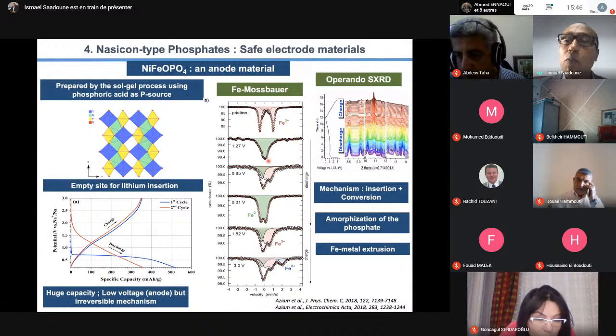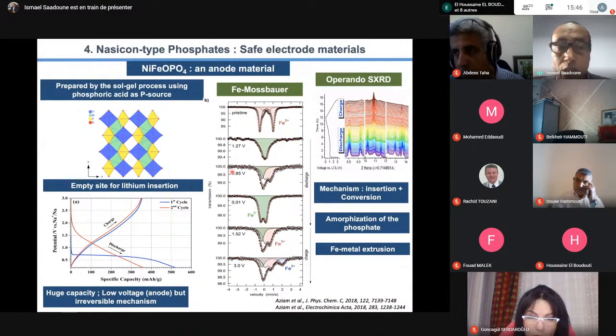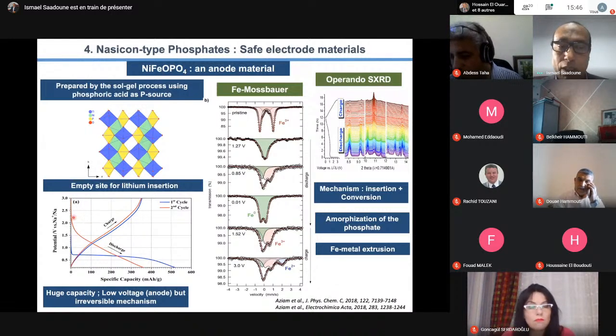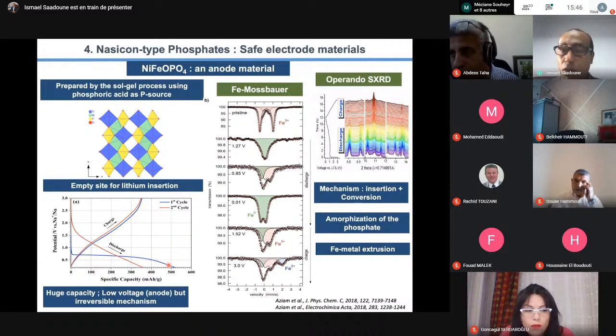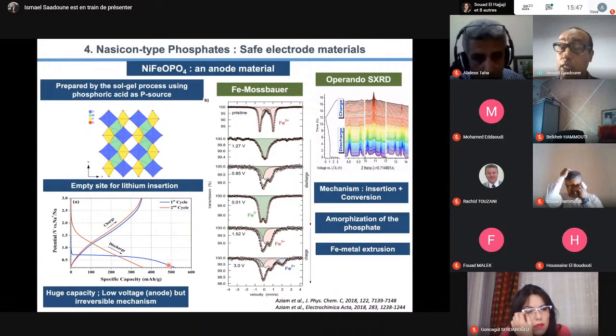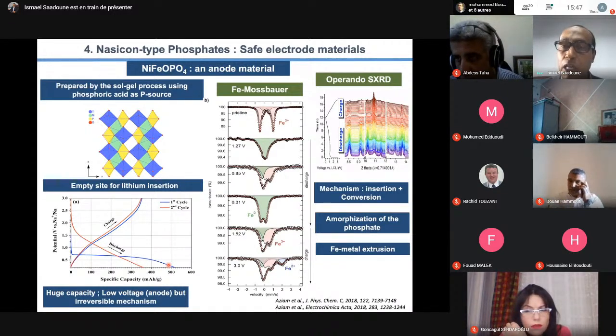So we did some operando synchrotron, and we see that during discharge, we first have crystallized material with some peaks, but after that, we get amorphous material. So we have amorphization of our phosphate. This was surprising because normally phosphates are crystallographically and structurally stable. But here, just by doing electrochemistry at room temperature, putting in current, we completely destroyed the structure.